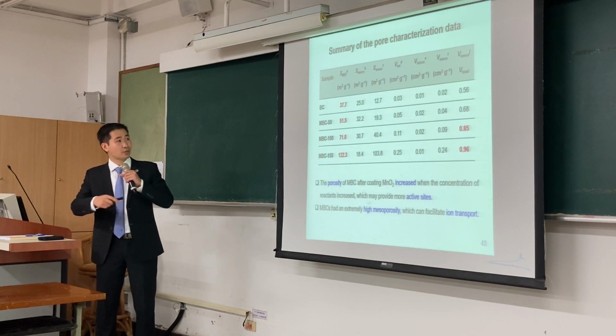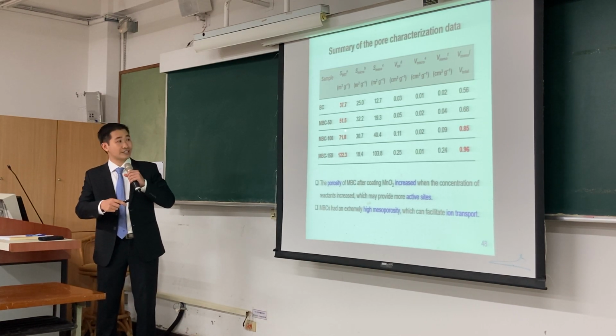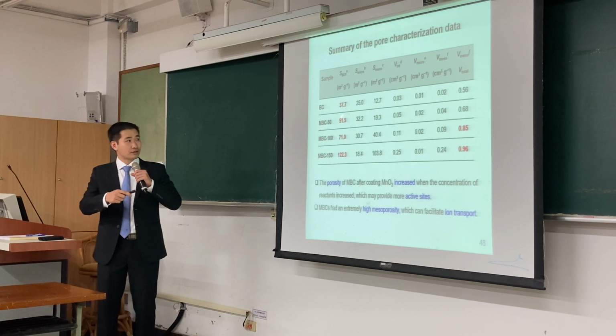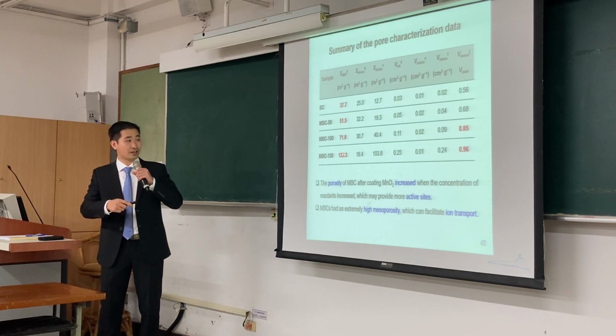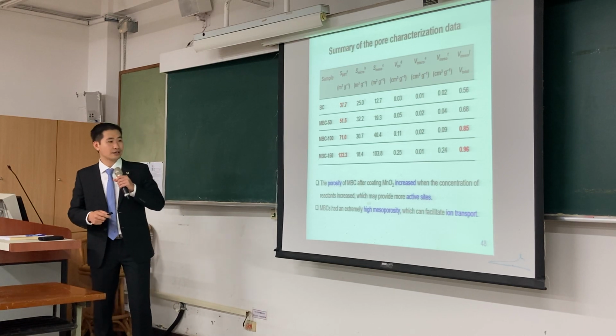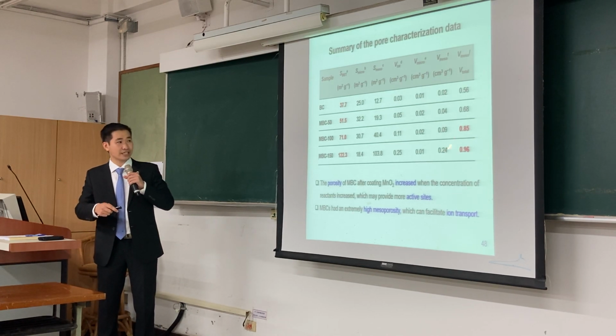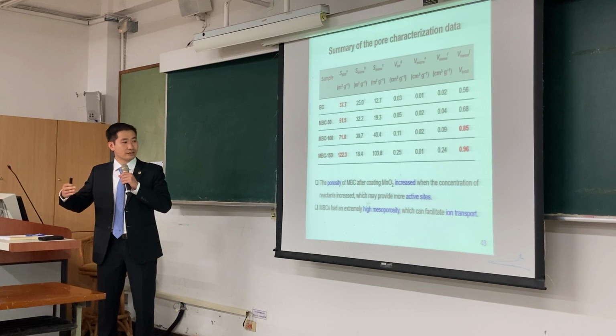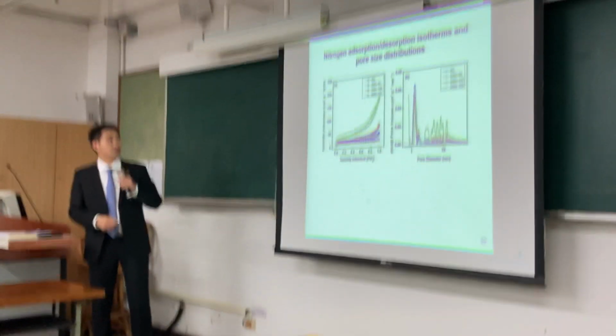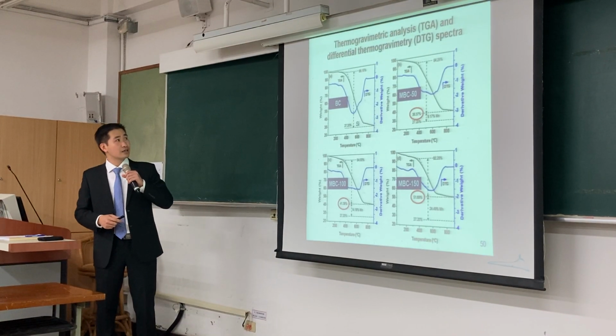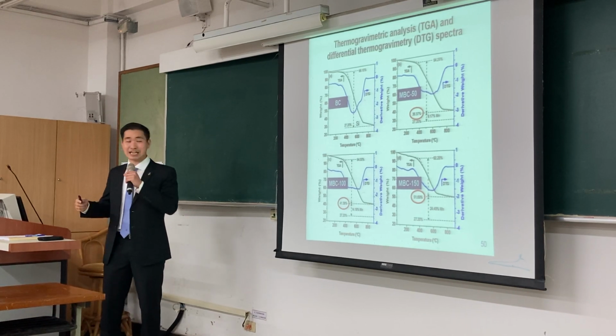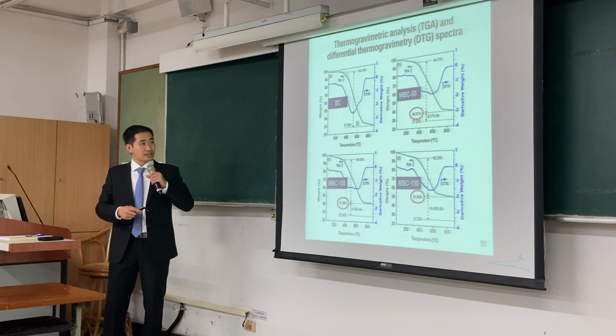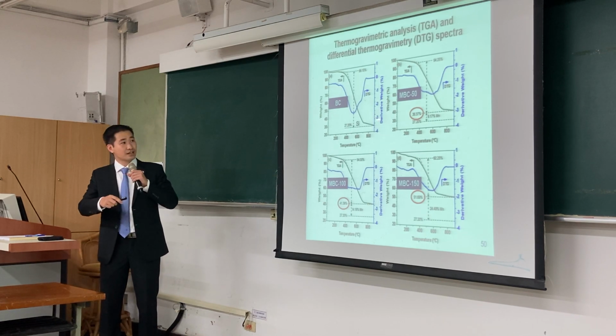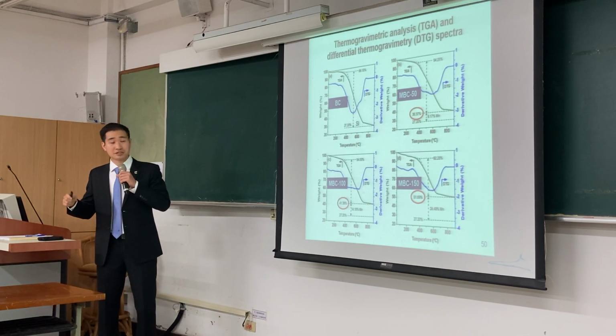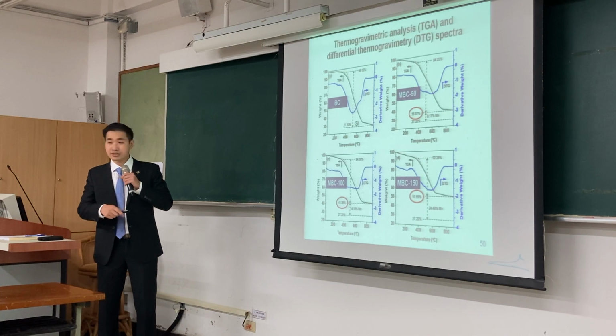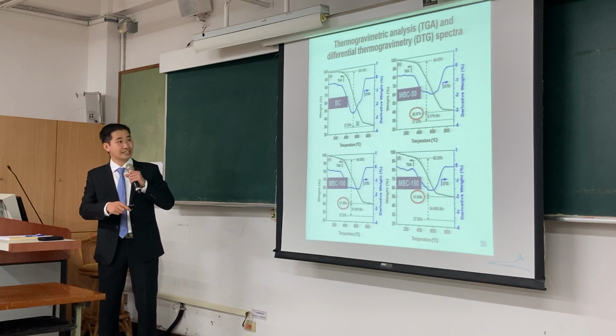As you can see, when the reactant concentration increases, the specific surface area increases, and high mesoporosity may facilitate ion transport. More interestingly, the TGA analysis presents the result that the residual mass of the sample increases when the reactant concentration increases.